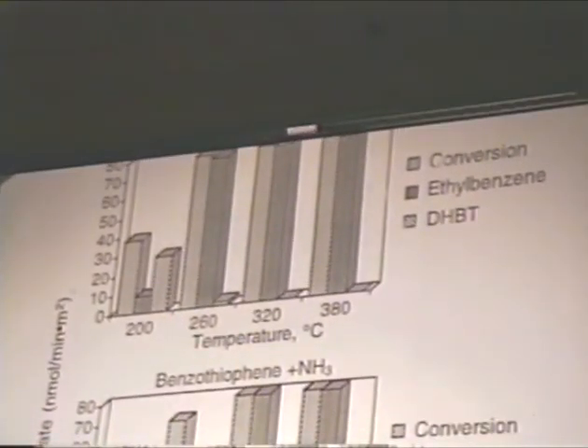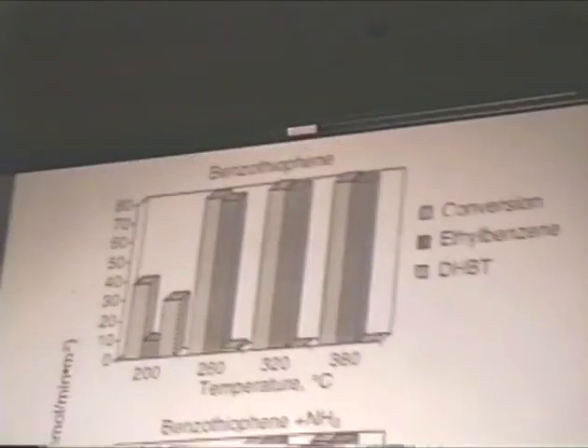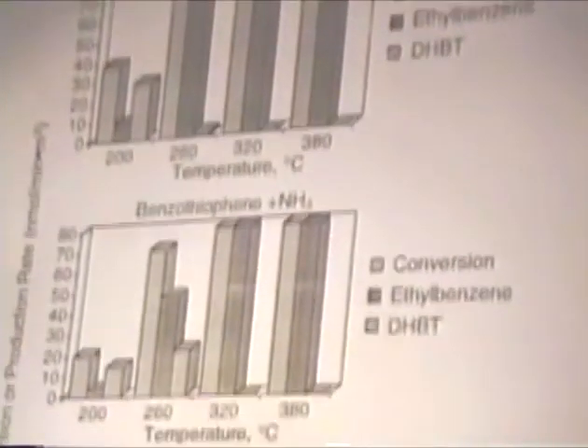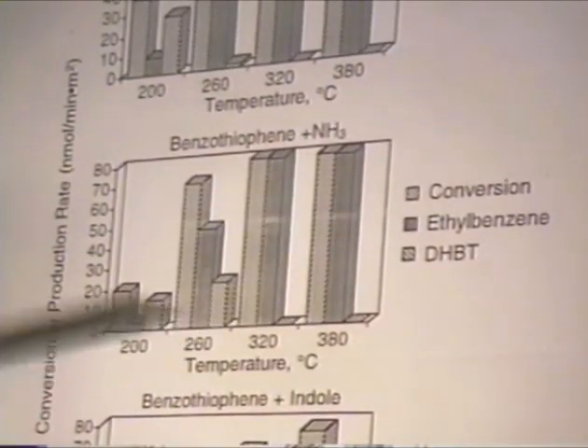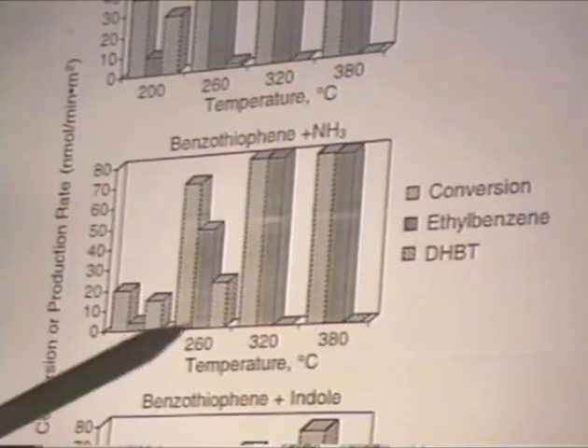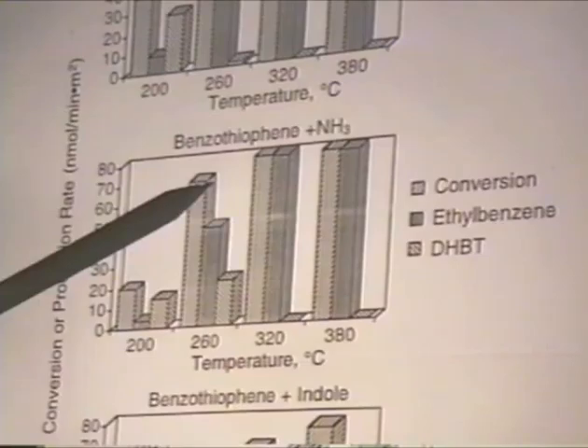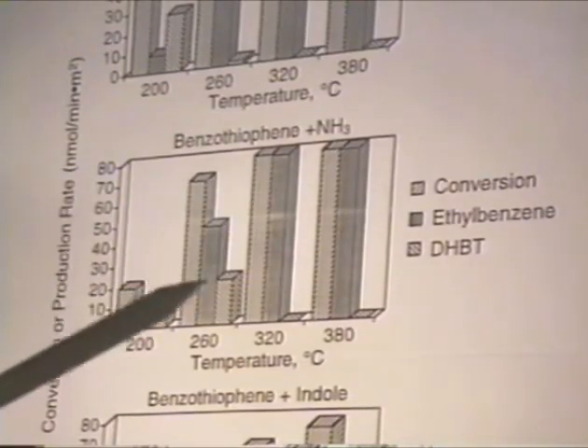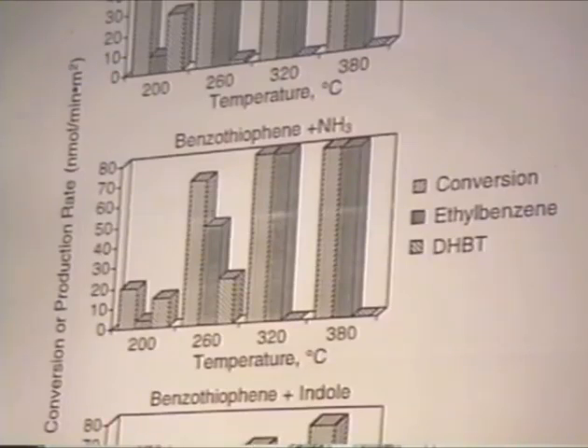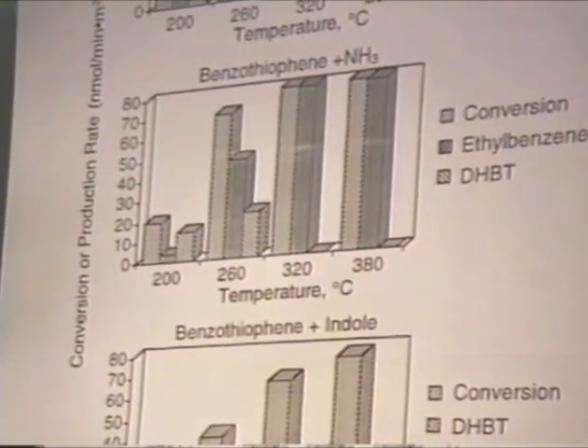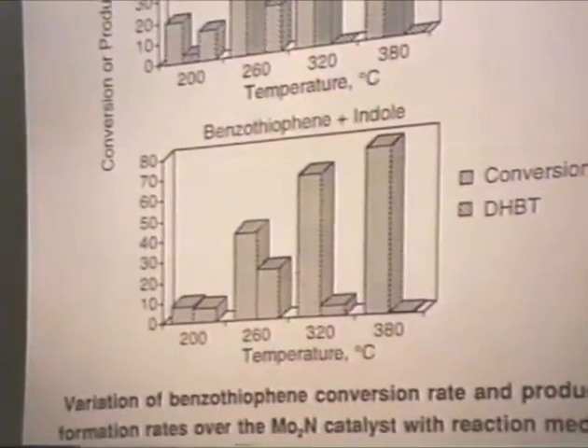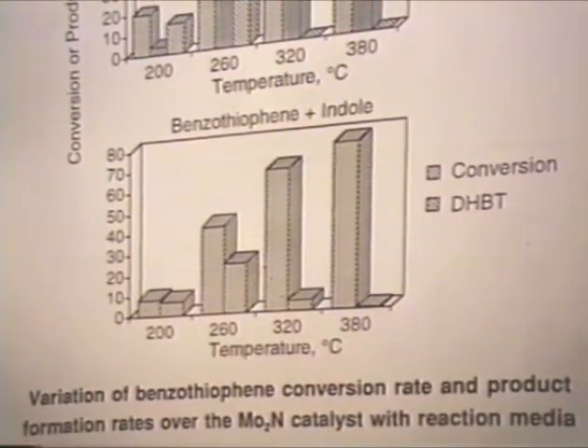Now, when we have ammonia present in the system, fed together with the benzothiophene, if we look at 260 degrees centigrade, we see some inhibition effect. We don't see it at the higher temperatures, but at 260 degrees C, conversion is less than complete. Also, there are significant levels of dihydrobenzothiophene. However, the major inhibition effect is seen when we feed benzothiophene and indole together. Actually, at every temperature, even at the highest temperature we have used, there is significant inhibition effect and also some levels of dihydrobenzothiophene.